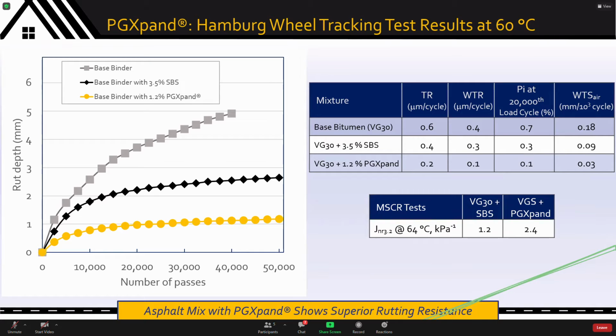What you can see is not just in rut depth as a function of number of passes, but by any measure of rutting resistance, the incremental growth rate, the PI, any number of terms, measurements of rutting resistance, the rutting properties of PGXpand are truly exceptional.